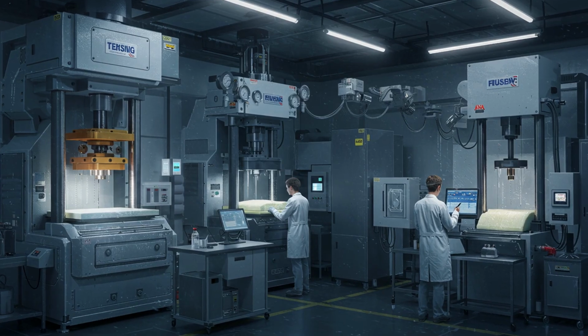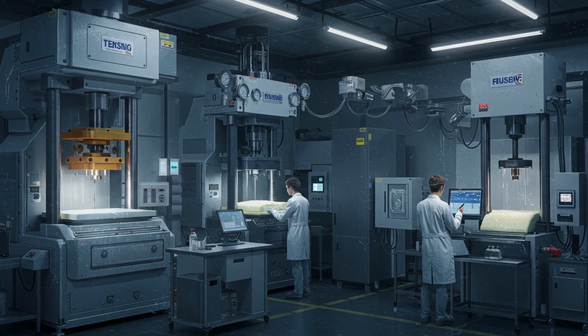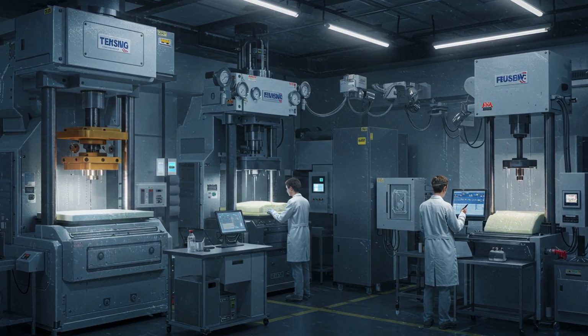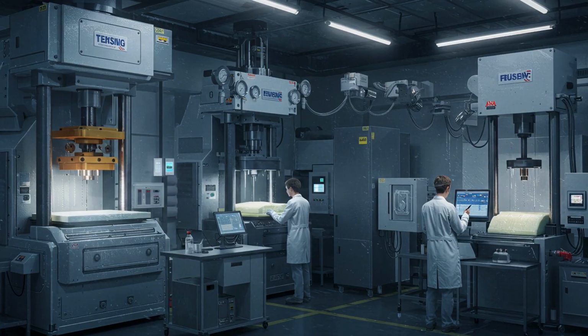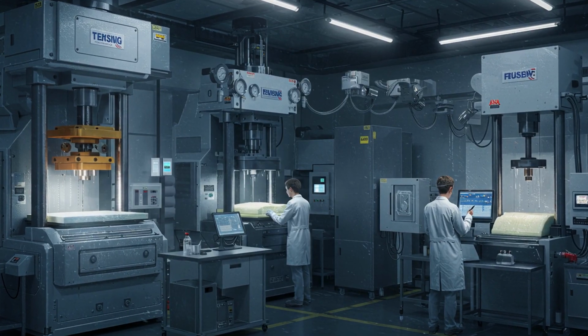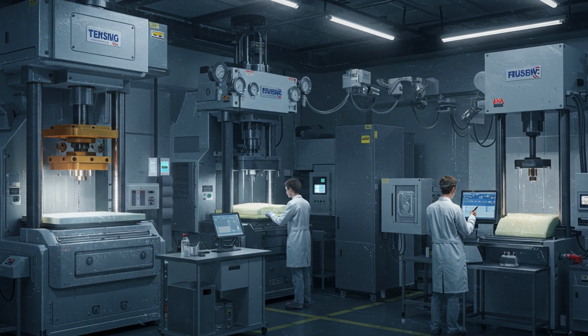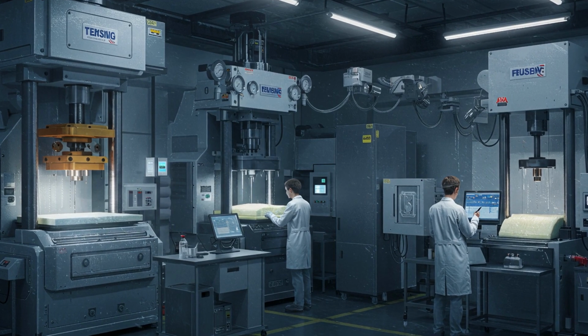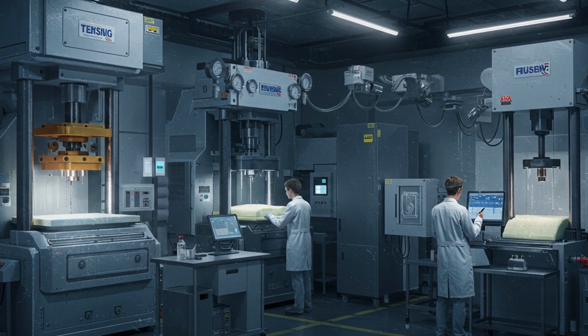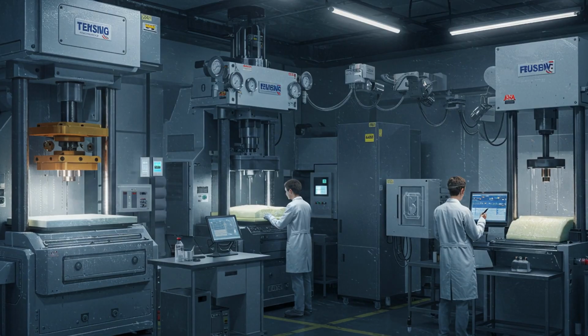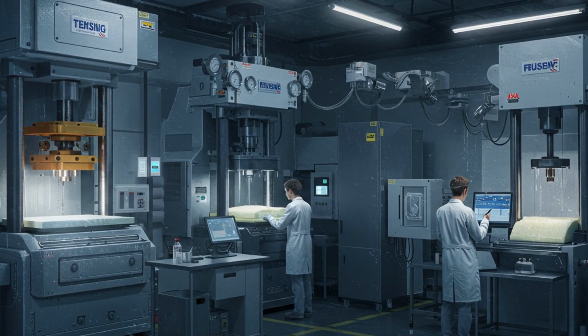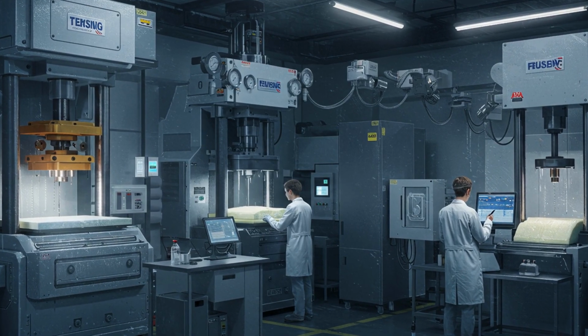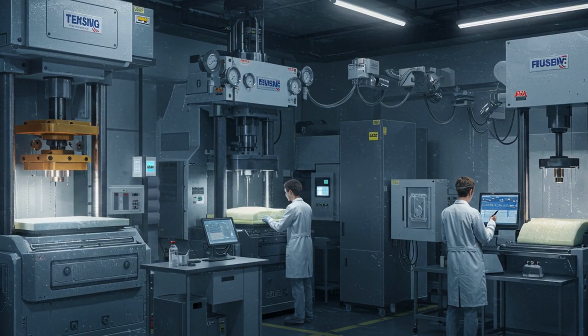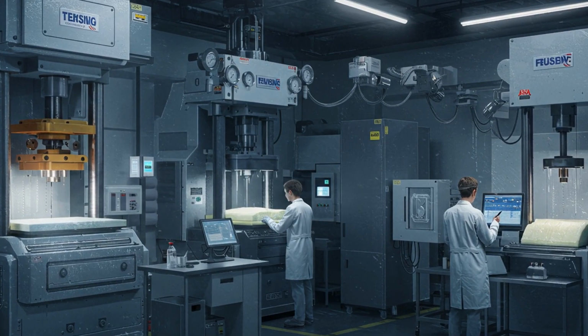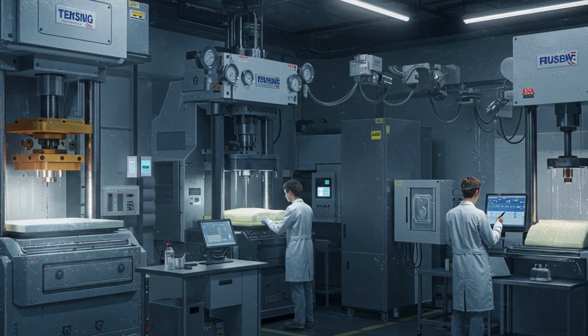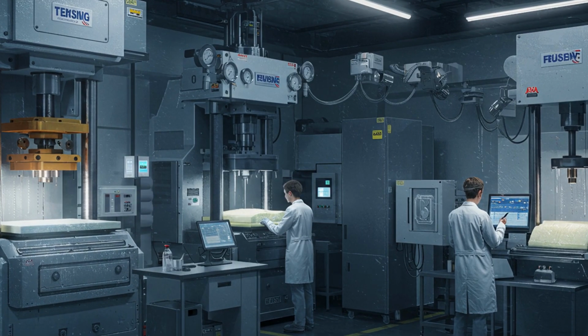Quality control is ruthless. Memory foam must survive thousands of sleep cycles, resist permanent set, and meet safety standards. Fatigue testing machines apply cyclic loads, thousands to hundreds of thousands of cycles, while sensors measure compression set and resilience. Indentation force deflection, or IFD, quantifies firmness in pounds at 25% indentation. Typical memory foams test between 8 to 30 pounds depending on comfort level. Recovery time is measured in seconds, how long until the foam returns to 90% of its height.